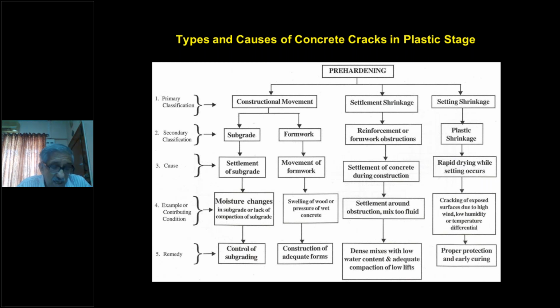And of course, if you are working in dry areas, I don't mean Gujarat, dry areas where humidity is low, concrete rapidly loses water from its surface. Cracks are exposed on the surface due to high wind, low humidity, or temperature differential. These are very, very important and most often occur because people don't take care of properly protecting the concrete at a very early stage. This is very, very important.